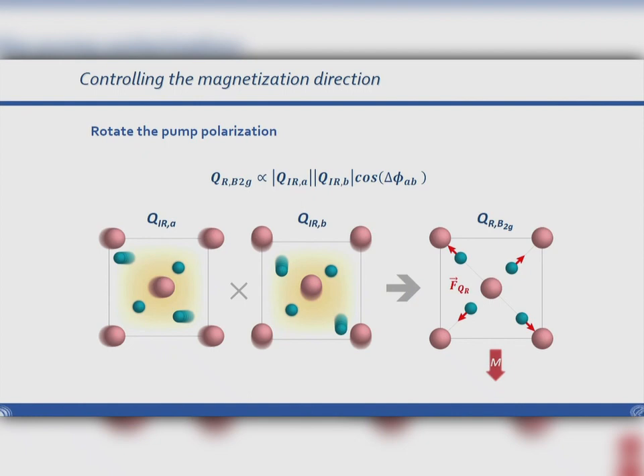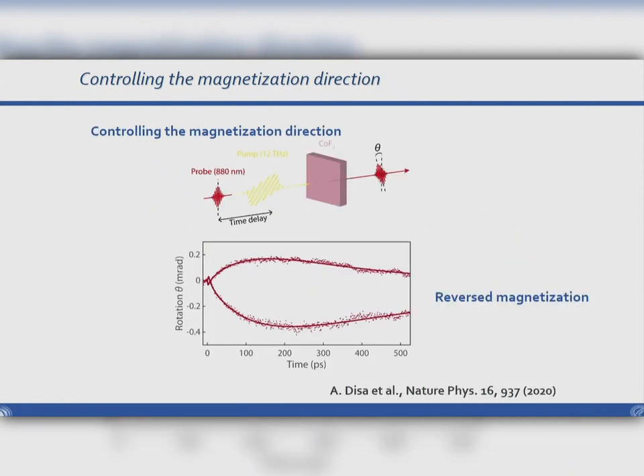On the other hand, because of this particular type of excitation where we couple to two phonons at the same time, by changing the polarization of the pump pulse, we can excite the two phonons with a different phase. And this would lead to the rectified atoms moving either closer to the cobalt or further away from the cobalt, yeah? So in that sense, you should be able to reverse the magnetization that you induce in this material. And indeed, this is what we observe.